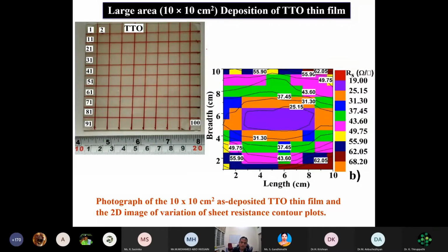Now, we also made a large area deposit, 10 centimeter by 10 centimeter, and then we measured the sheet resistance. And remember here, when I make an aerosol for deposition, it goes like a cone, an inverted cone. So when I keep my substrate here, there is no guarantee that the entire substrate will be uniformly sprayed. So always there will be some variations, and temperature gradient also will be there. So you see that when I make a large area, only the center part is good. Center part is around 18 to 19 ohm here. This color coding you can see here. Violet color is at the center. When I go to the edge, you see dark blue. Dark blue color is around 55 to 62 ohm. So the sheet resistance is good only in the near center part of the 10 by 10 centimeter. At the edges and all, it is going to vary. So we have to overcome these issues.